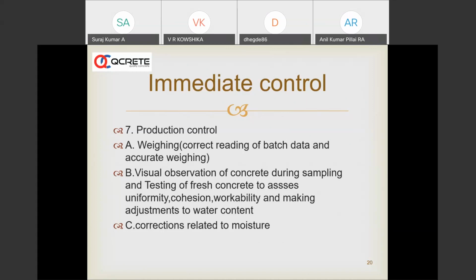On dry days, like in hot summer, when we are very sure that there is no moisture, maybe the moisture can be fed only one time when we are sure that there are no big changes in the moisture content. But otherwise, we need to have very strict control on 12 mm, 10 mm, and sand moisture, and it has to be very carefully done, especially if we are doing high grade concretes above M40.